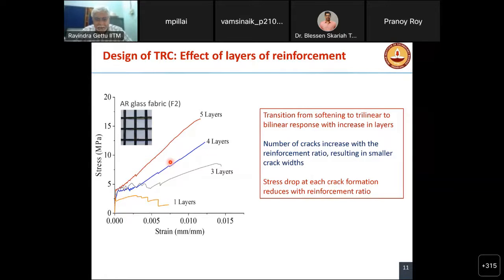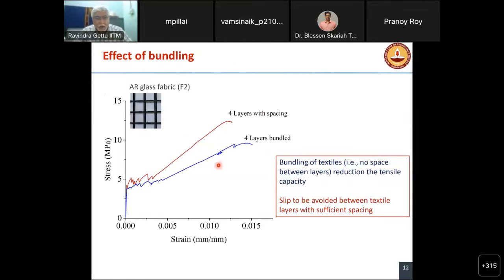There are other things also which matter. For example, how to put the layers. If you put all the 4 layers together, you find that the response is different. You get less load because what happens is the layers start sliding on each other. So it is better to put layers with some spacing, like we would do for reinforced concrete. Better to have layers and not all bundled together, so that slip is avoided. So these are things that we have been learning as we go along.